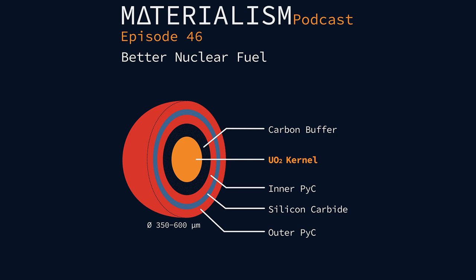to see what is the limit of operation until these particles actually start to fail. And so they'll typically try to see how long they can last. And nominal times for these tests are about 300 hours is what they typically try to guarantee. Because hopefully at that point you figured out some sort of remedial method of stopping this reactor from going off. So 1600 and 1700 are fairly stable, but 1800 is really where failure is pretty imminent.